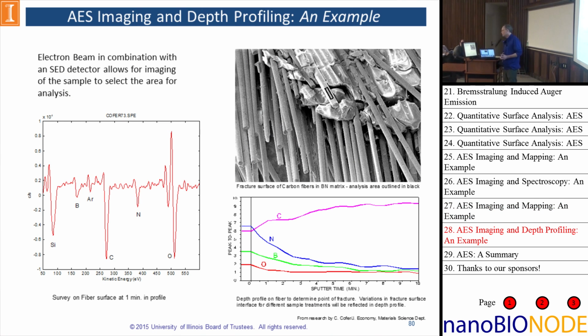Here's an example where we're going to combine spectroscopy, imaging, and depth profiling. So here, we're studying a carbon fiber in a boron nitride matrix. A lot of the times in these composite materials, the properties of the composite relate to the interaction of the fiber with the matrix. And so sometimes the producers of these fibers will want to modify this surface to vary the properties or the interaction between the two. And so we can, first of all, collect an image, select the fiber we want to zoom in on, collect the spectrum, identify all the elements that we have present, then look at these elements as a function of depth as we sputter into them.